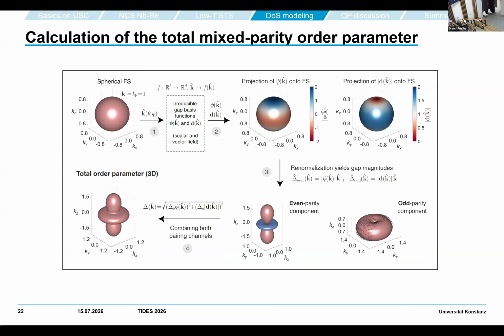One important assumption we make is that we assume a spherical Fermi surface. We take these irreducible gap functions, project them on the Fermi surface, and calculate the resulting order parameter. The two shown here gave us the best agreement with experiment, but we tested all combinations of the zoo shown in the table before, and then combine these two components to calculate a total order parameter, which in our case looks like that.